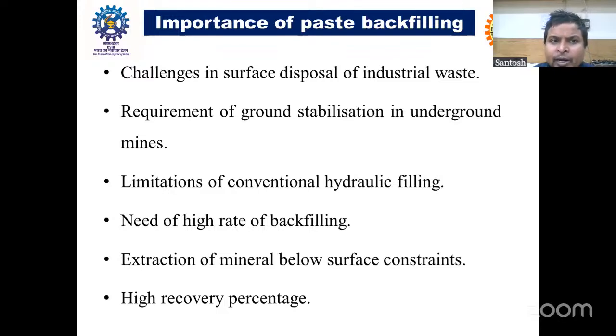Now, why is paste fill required? Though industry has hydraulic filling, and people are doing hydraulic filling and cemented hydraulic filling, it was the need of the industry to improve and increase production, at the same time increase safety, and at the same time dispose of the tailings generated from the mill in a large volume. Considering all those issues, and also the many limitations of hydraulic filling, one more requirement is that the stopes, the voids being created, need to be backfilled quickly. That means a high rate of backfilling is required, even to extract ore below important surface features. So considering all those requirements, people started using paste filling.